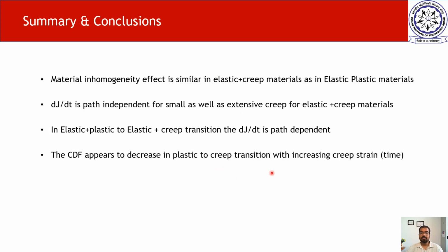And at the end, I would like to summarize that for elastic creep and elastic plastic creep condition, we found, and also in the other work, we have found, that dJ/dt shows path independence even in the small scale creep condition, and it is related to the true crack driving force unlike CT integral, and it becomes equal to CT integral for extensive creep condition. So in extensive creep condition, this is equal to the CT integral, and crack driving force appears to decrease when the crack transition happens from plastic to creep material, but this is a different result from what we expected, and we need more results to confirm this.